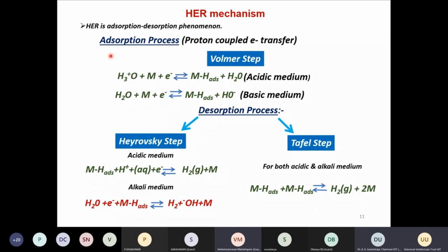Briefly, I will explain the hydrogen evolution reaction mechanism. It has an adsorption process, which is a proton coupled electron transfer process, where you can see the hydronium ion on the metal, which is your catalyst, and you have an electron. So metal hydrogen gets adsorbed on the metal, and this happens in acidic pH. In the base, it happens with water and a metal, which is your catalyst, and then the same reaction happens, and this is called the Volmer step. But here what is needed is the breaking of water into H plus and OH, whereas in the case of acidic pH, you already have a hydronium ion.